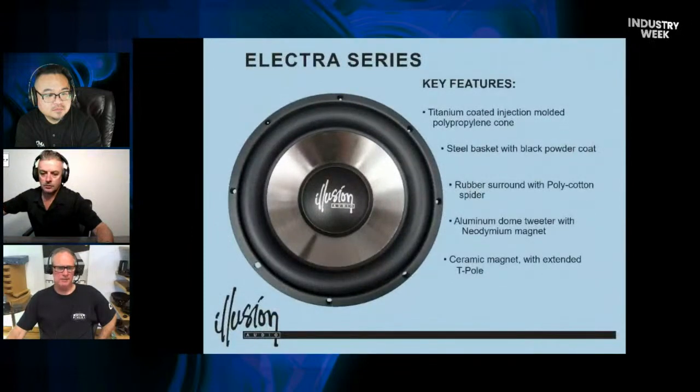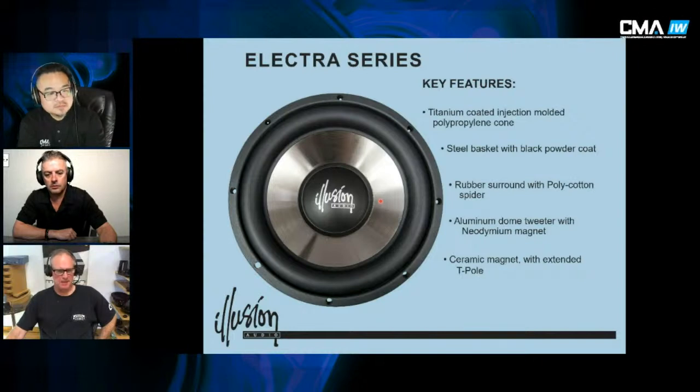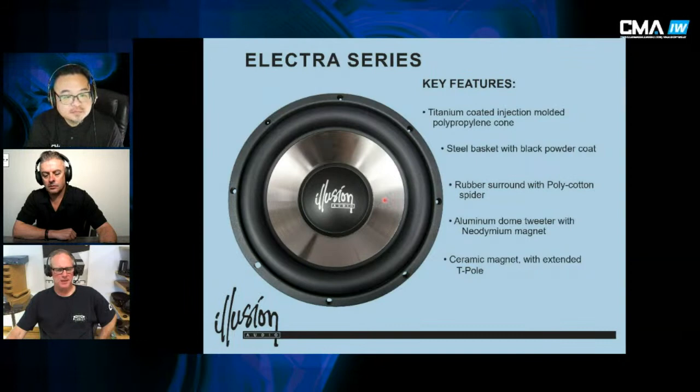Okay, entry level, our Electra series. These subwoofers were actually originally designed for studio monitor use. So those are very stringent performance applications for distortion, loudness, and flatness of frequency response. And then to go from the studio to the car, we simply changed from a paper cone to a polypropylene cone, but kept the rest of it. So in this case, the entire line, it's an injection molded polypropylene cone, so it's variable thickness, thick at the center, progressively getting thin to the edge, so you can tune the breakup characteristics.